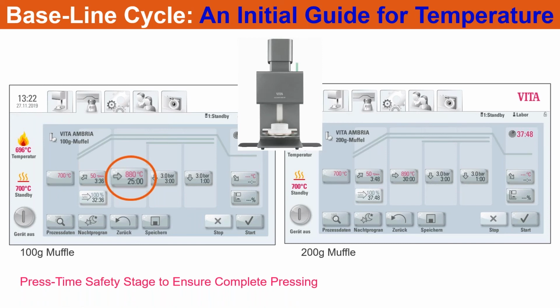Usually you should be able to have anything pressed out within about 4 minutes, 5 minutes at the max. We set it up so you have a 4-minute process. Most smaller rings, and even most 200-gram rings, press out in less than 3 minutes. But if it goes through all 3 minutes, maybe your temperature is a little bit low, the viscosity of your press material is a little bit harder, gummy, if you will, and it's taking more pressure to press that material, it will go through that 3-minute cycle and then continue on into the secondary press cycle. So it's got like a safety valve there, if you will, as far as the pressing goes.